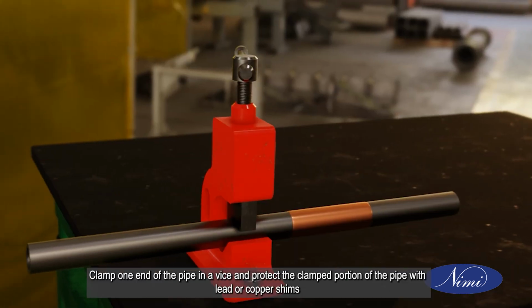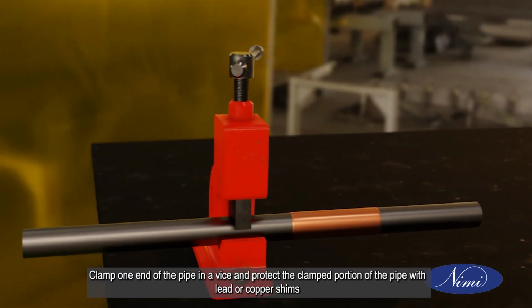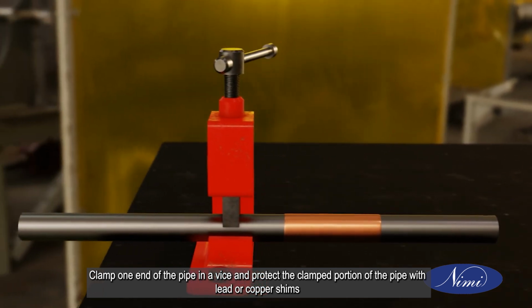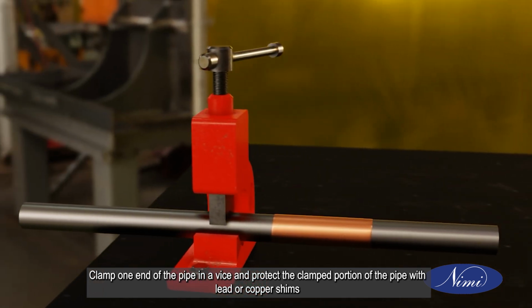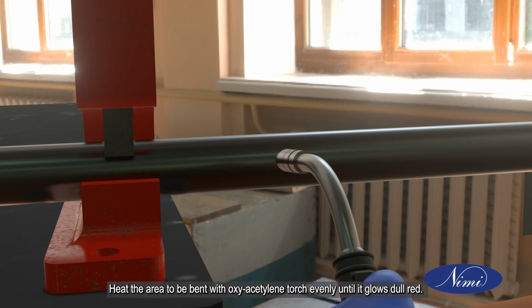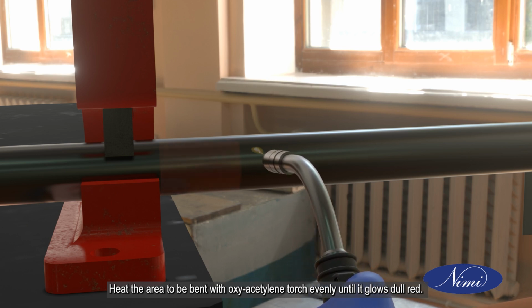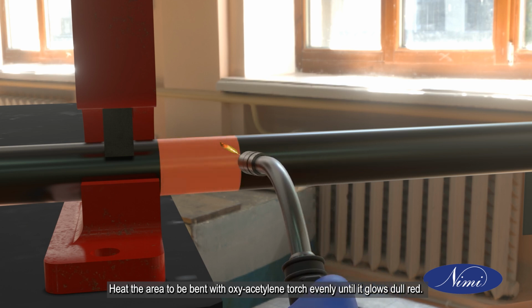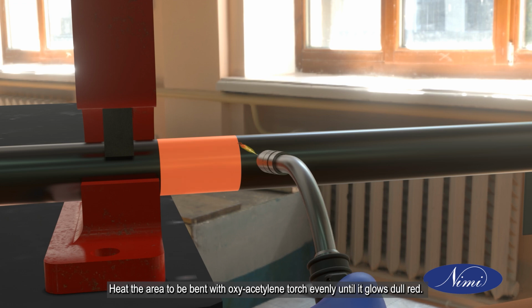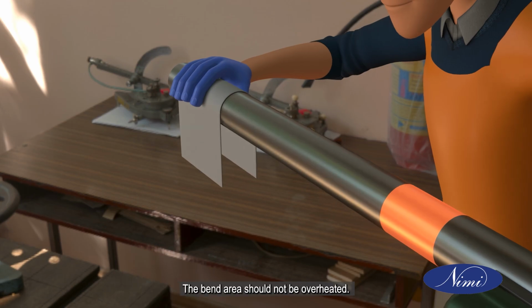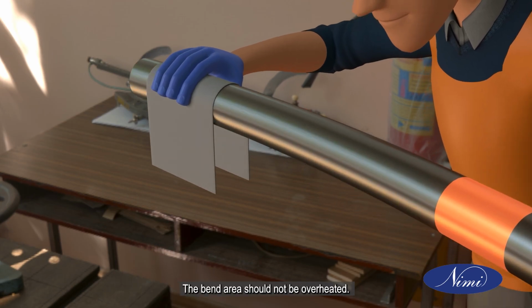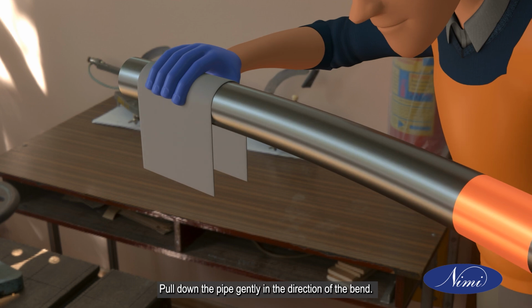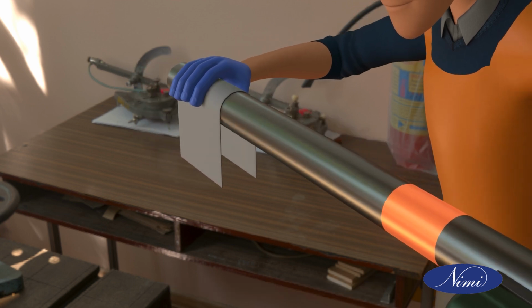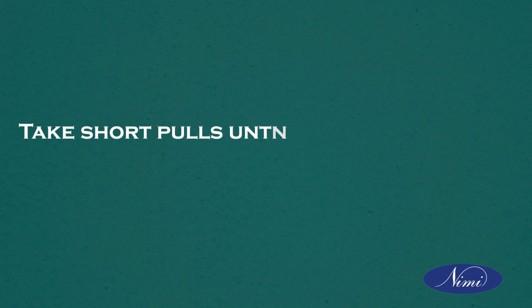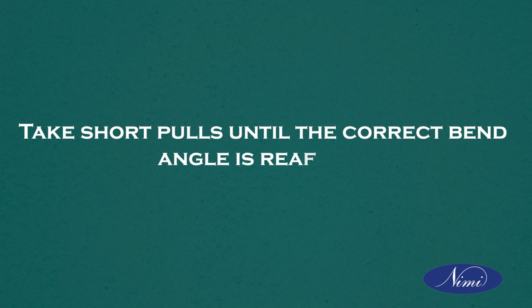Clamp one end of the pipe in a vise and protect the clamped portion of the pipe with lead or copper shims. Heat the area to be bent with oxyacetylene torch evenly until it glows dull red. The bend area should not be overheated. Pull down the pipe gently in the direction of the bend. Take short pulls until the correct bend angle is reached.